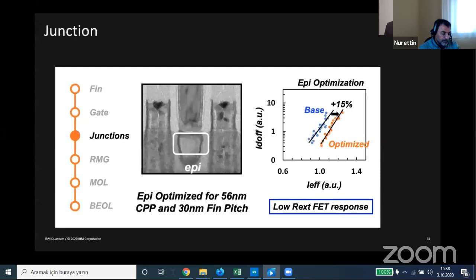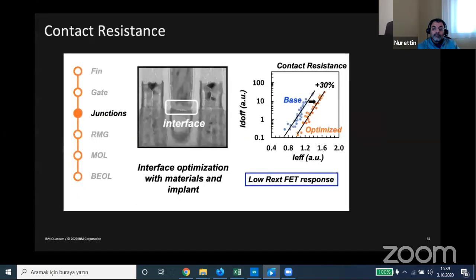Next was the junction optimization. The way we form the junctions in this technology is not through implant, but through out-diffusing dopants from this epi layer into the channel using a thermal process. So it's through out-diffusion. So this epi was optimized to achieve the best junction possible in terms of short channel effects and also resistance, link-up resistance from the source drain to the channel. And you can see here that the benefit was quite significant compared to our base process, 15% by optimizing the epi for that.